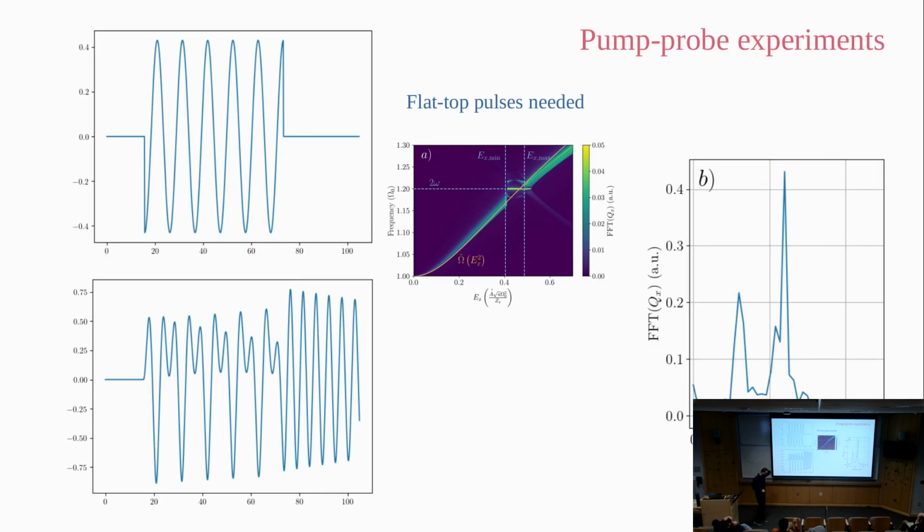What is important is that this requires relatively high fields, and such high fields right now you get in pulses. So it's important to see whether your idea survives not having a continuous drive, but just pulse drive. And actually it does, but there's a caveat. Here it's important that you have a well-defined amplitude for your signal. If you have a Gaussian pulse, of course, the amplitude will have some central value, but then it will strongly decline at the ends of the pulse. So what you need is a flat top pulse that preserves the amplitude. It can be very short, just 6 cycles here, or 5 cycles, but it has to have a nearly constant amplitude. And with such pulses, you can indeed trigger it.